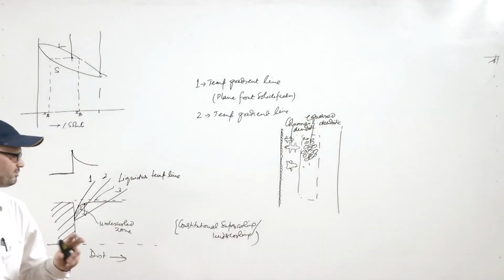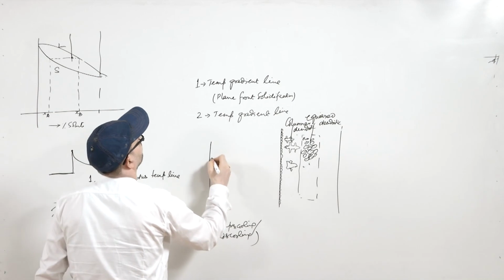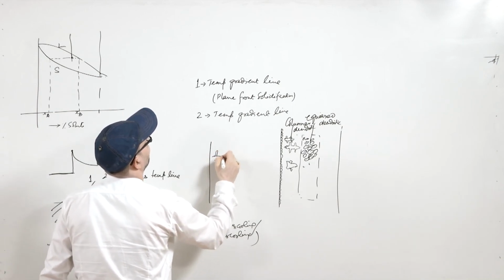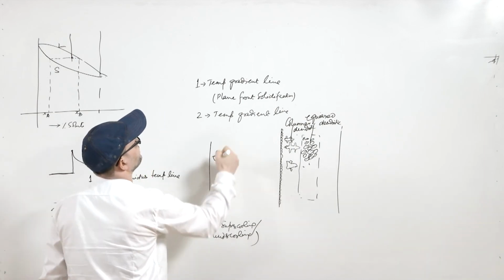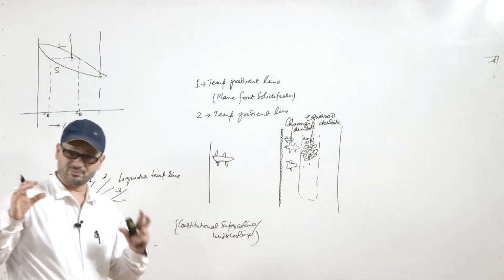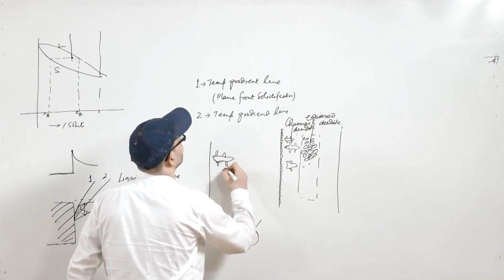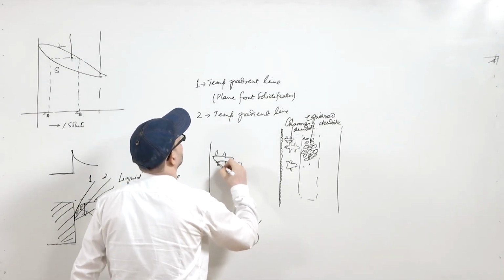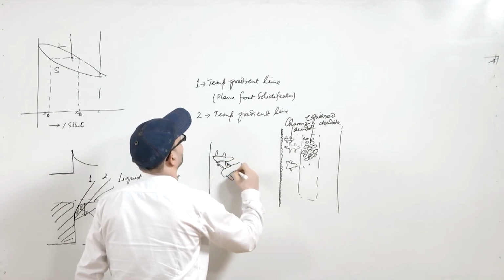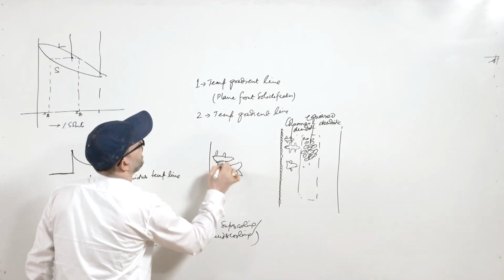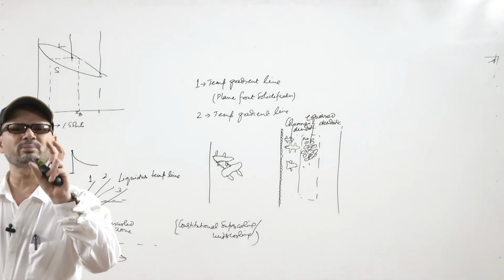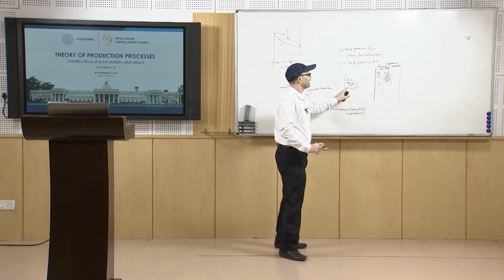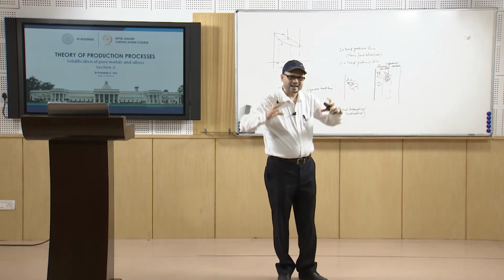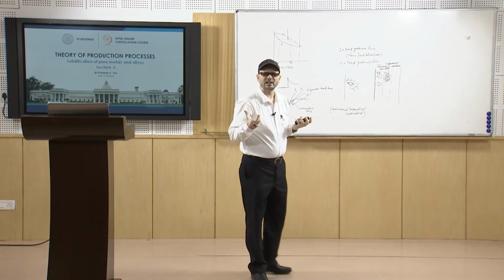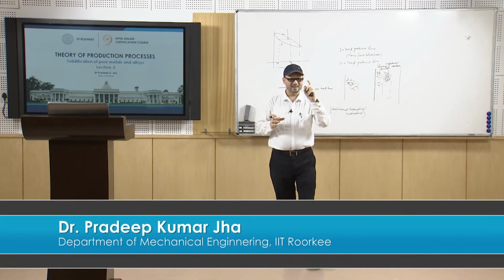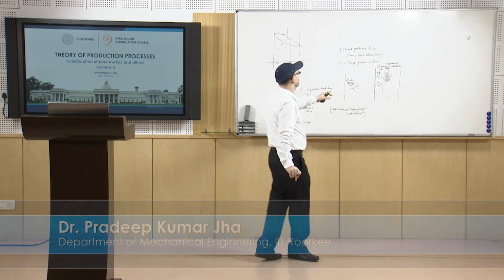So, if you have the wall here, you will have this kind of structure, where this is a primary dendrite and these are the secondary arms. This situation is very much deleterious, because when you have such dendrites, suppose you have another dendrite whose arm has gone like this. Now, if liquid is entrapped in between these arms, then this liquid is the source of shrinkage defect, because there is no plane front solidification. It is a case of tree-like structure formation, and in between the arms there may be entrapment of liquid steel or liquid material, and that may be the source of some defect. So, that is a case of dendritic type of solidification.